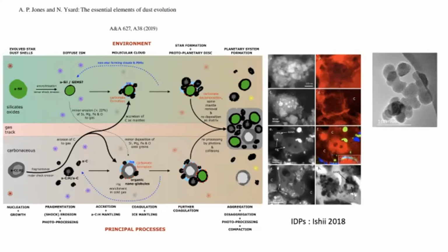If you look at the transmission electron micrograph of the carbon nanoparticles we have studied, actually they are bigger than the primary particles at 20 nanometers, in fact 100 or more nanometers in size. And we believe that the sticking coefficient of a big grain is that of the small grains that make it. What is important is the size of the primary particle and not the size of the aggregate.